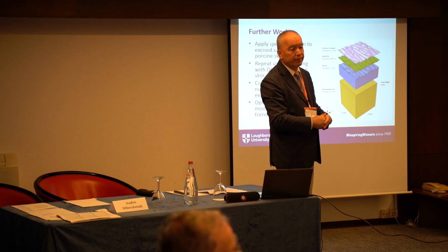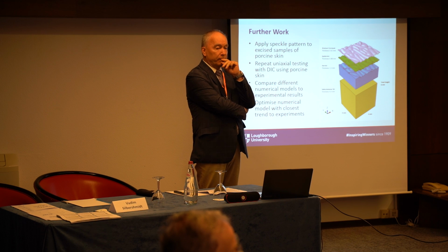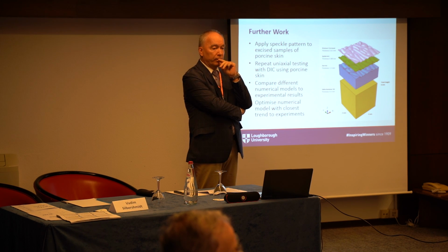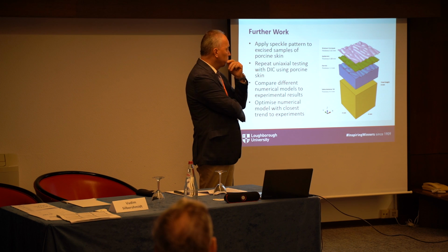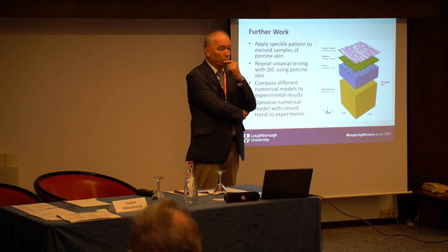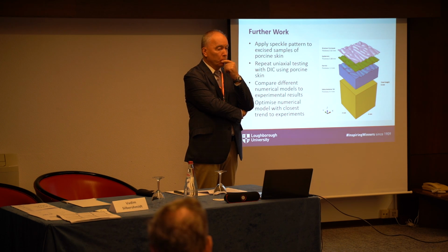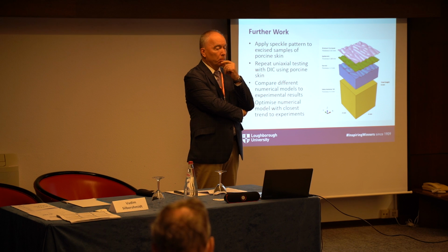Thank you for the very interesting talk. I was wondering on the modeling part. First, why did you specifically choose those models? And did you consider using, for instance, microsphere models or approaches for which the shear modulus of the network is a relevant parameter, and there are approaches that consider the microstructure of the networks, phantom models, Gaussian approaches, tree-like structures? Did you ever consider doing this, and also relaxing, for instance, the affine deformation hypothesis to allow the chains to deform in a non-affine way?